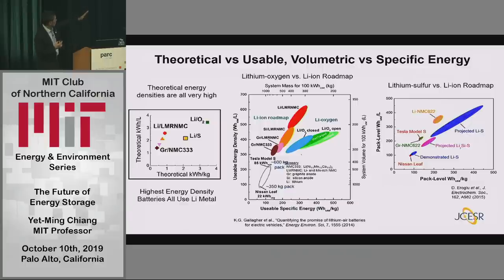But what you see is that on this theoretical energy plot, the four to the left are what we're working towards in lithium ion batteries today. That's what we use. And then you have two far out to the right. And theoretically, the energy density is fairly enormous. This is, let's say, 3,000 watt hours per kilogram. And the Tesla Model S pack right now is close to about 150 watt hours per kilogram. So 3,000 to 150, right? And so there's a really large gap between theoretically what chemistry can do and practically what we get out of it, right? And there are a lot of reasons for that.